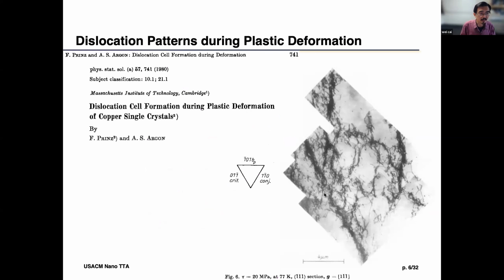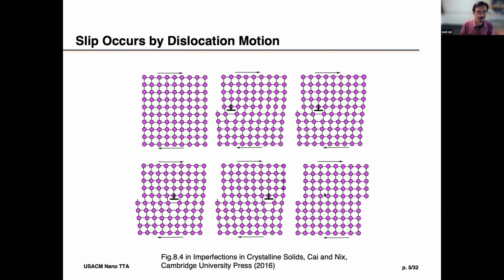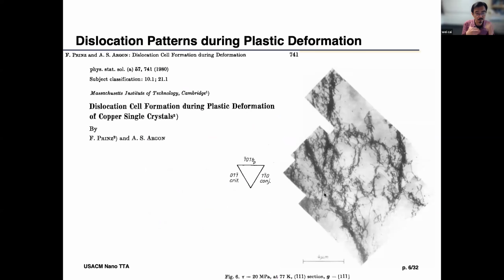Now, that is a single dislocation, and that does not fully explain the crystal plasticity behavior. What happens is that the dislocation lines form patterns at the multi-micron length scale, and that really obstructs further motion of dislocations, and that gives rise to the strain hardening behavior that we are trying to explain.